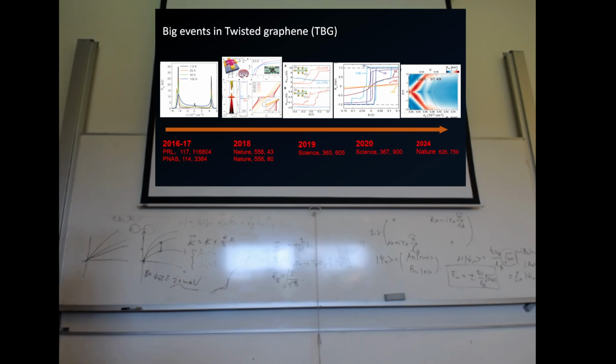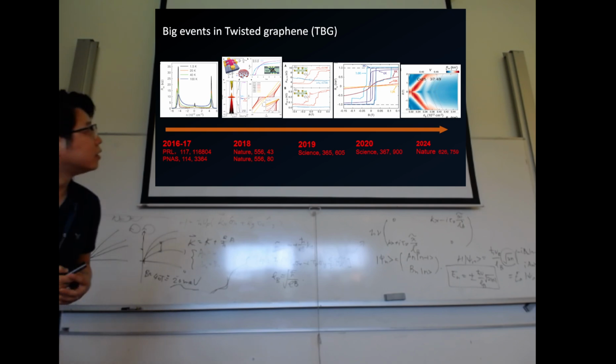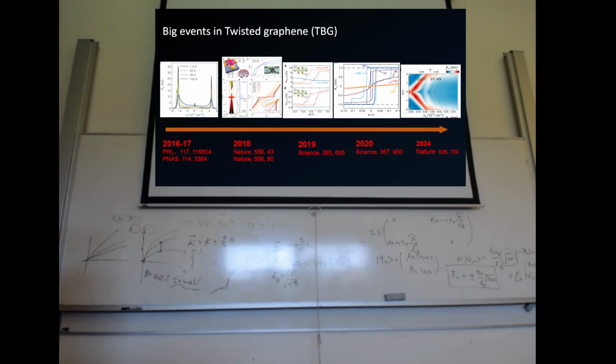And this year, in 2024, there were even more interesting papers coming out, using material systems such as twisted MoTe2 or ABC-stack graphene, five-layer graphene. They can see fractionally quantized Chern insulators at zero magnetic field. So the plateau is not even an integer, and now it can be a fraction, for example, 2/5, 3/7, and 4/9, and so on. They're mimicking exactly the same physics that people were studying in the 1980s and 1990s, 30 or 40 years ago at very high magnetic field, but now everything is happening at zero magnetic field, of course at very low temperature. And this is a very important branch of condensed matter physics in twisted-angle graphene.